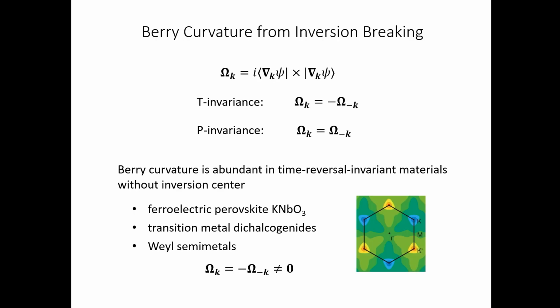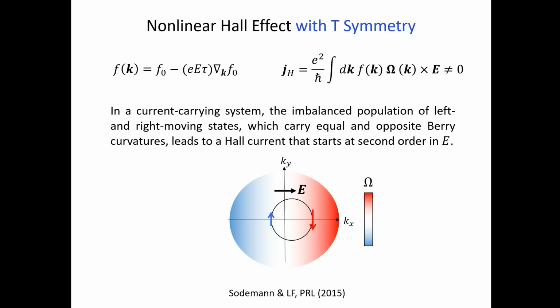On the other hand, I've always been interested in these inversion-breaking materials, time-reversal symmetric but inversion breaking. In that case, Berry curvature can still be present. It can, in fact, be very large. Some examples known from before are transition metal dichalcogenides. Another example is graphene on a boron nitride substrate. In all these cases, there is a strong Berry curvature at the Brillouin zone corner. But again, they take opposite signs at the two valleys, K and K prime. So the total Berry curvature vanishes, and there's no anomalous Hall effect.